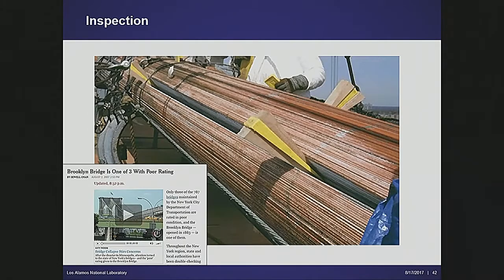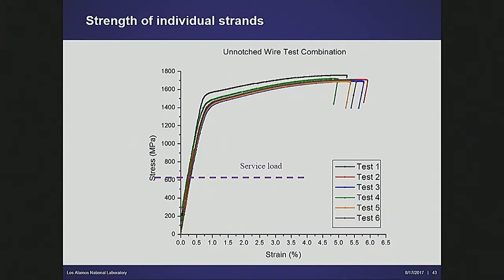One of the questions that relates to the strands is, if you've got a bundle of strands and the one in the middle breaks, does that mean that it no longer contributes to the load-bearing capacity of the whole bridge? In practice, what actually happens is that if the strand in the middle breaks, because it's clamped at different locations, even though there's a break right here in the middle, some distance away from that break the strand is still contributing to the load. How far that distance is feeds into the calculations and relates to the models as to whether or not you should take the bridge out of service. Pretty big deal.